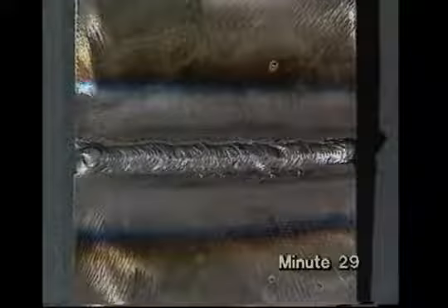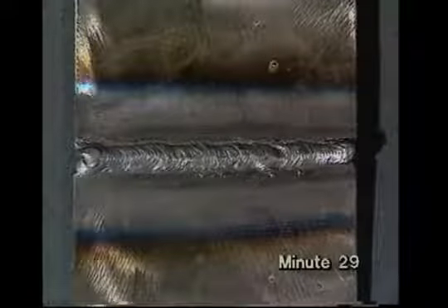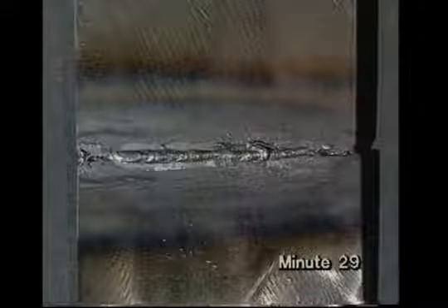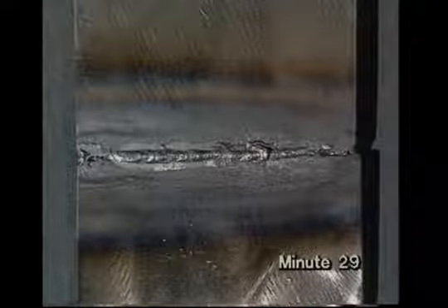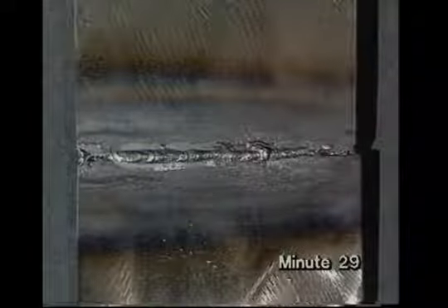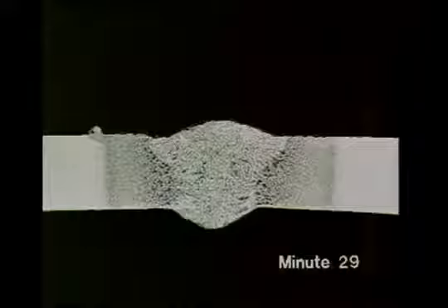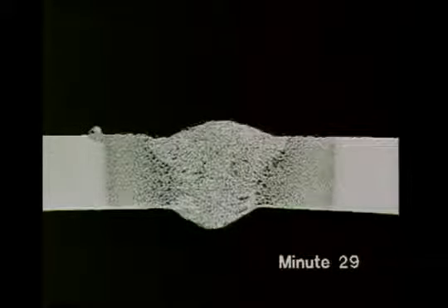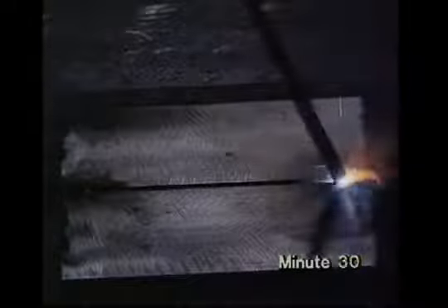This should leave a weld which extends beyond the gap between the plates. And when you look on the back, the weld metal should have gone right through and just penetrated beyond the surface. The macro section shows the smooth top and bottom profiles, and there's no sign of the original edges. But if the gap was too large, or the current too high, you would burn a hole.